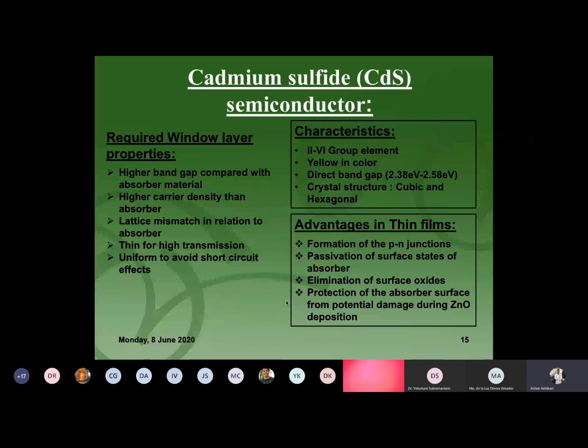The hexagonal crystal structure of cadmium sulfide is preferred over the cubic one because of its stability and high band gap. We require a higher band gap compared to the absorber layer to transmit photons from the window layer to the absorber layer. It has the advantage of forming a p-n junction, passivating the surface of the absorber layer, eliminating surface oxide or selenium, and protecting the absorber layer from the deposition of zinc oxide.